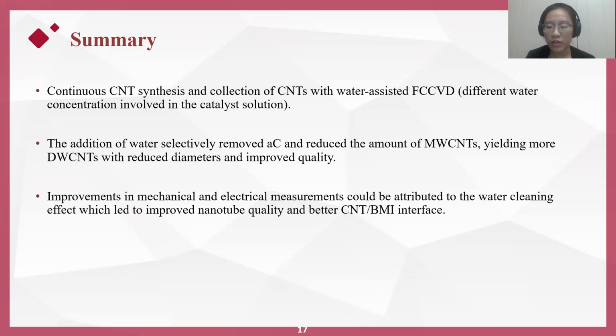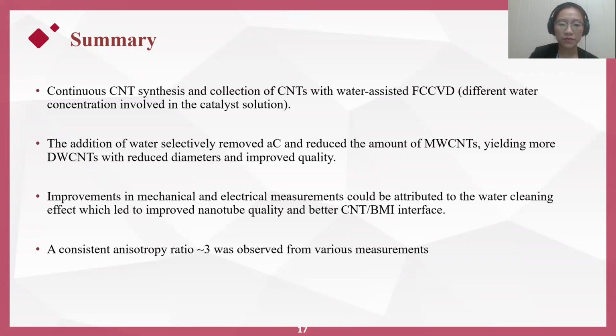could be attributed to the water cleaning effect, which led to improved nanotube quality and a better interface. A consistent anisotropic ratio around 3 was observed from various measurements as a direct measure of the stretch-induced alignment.